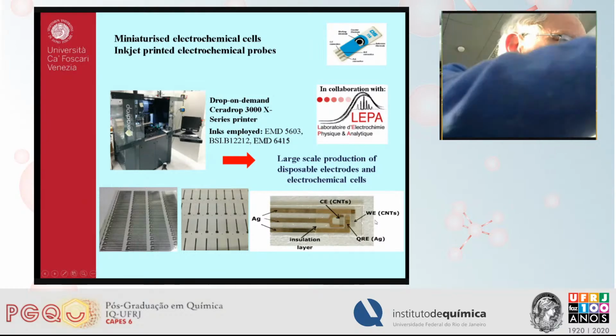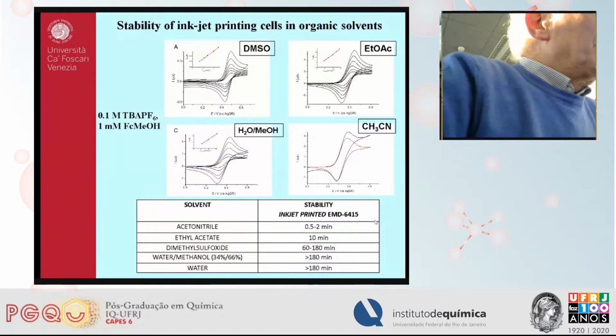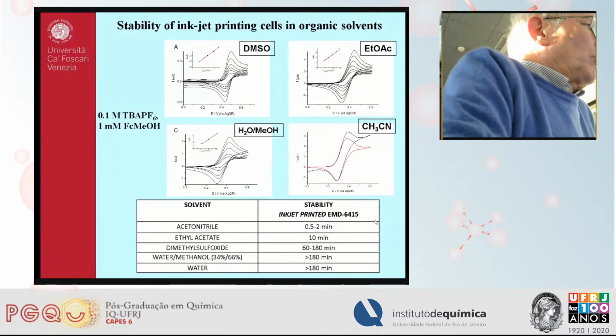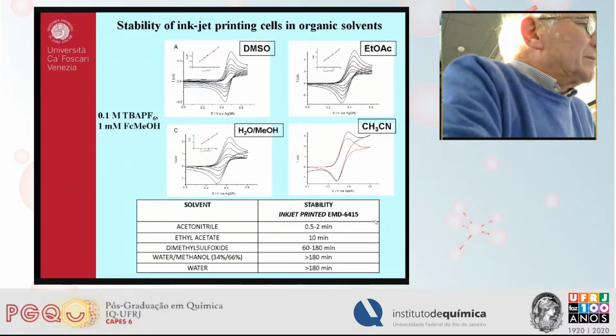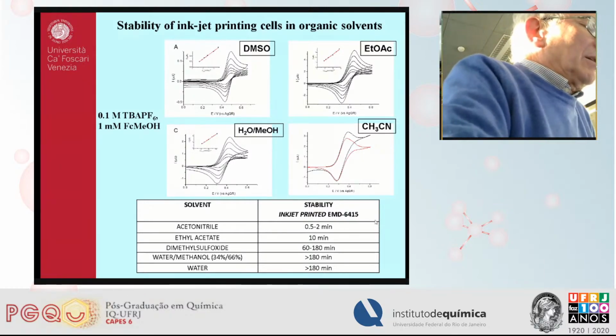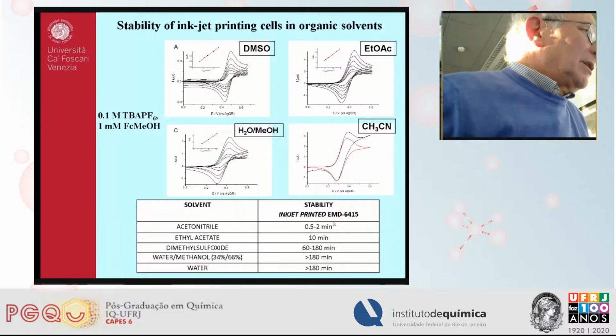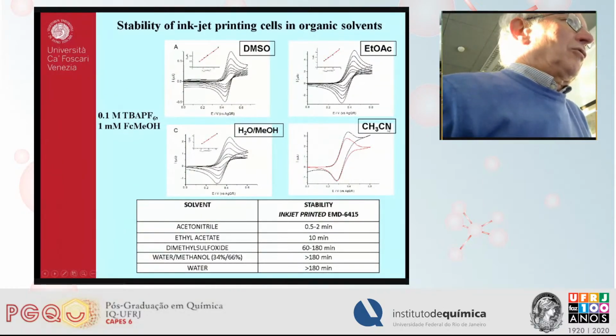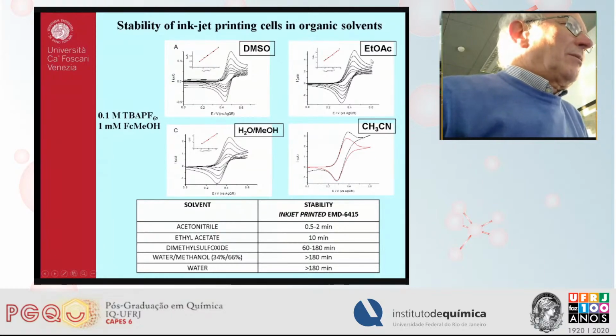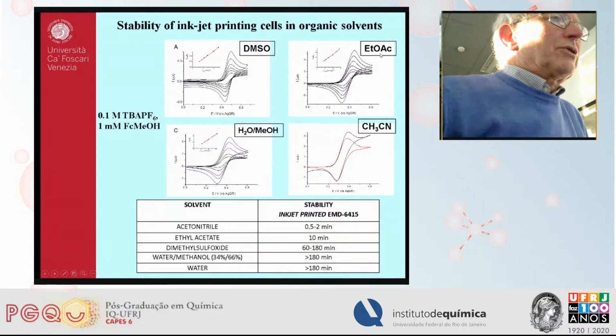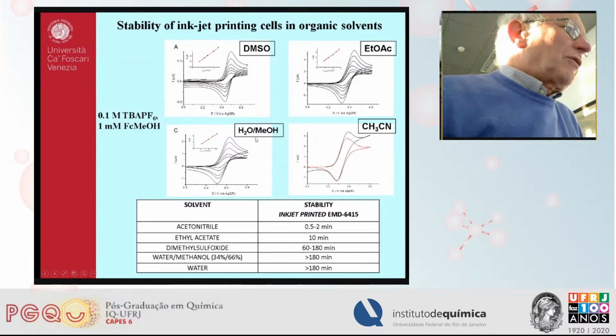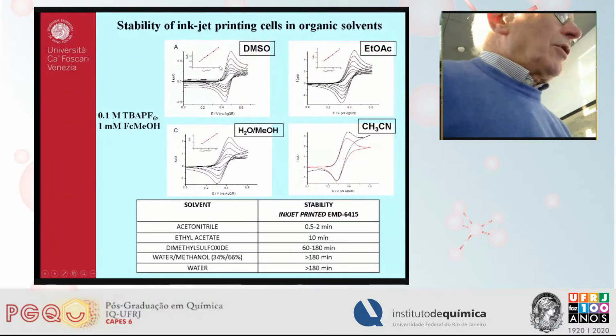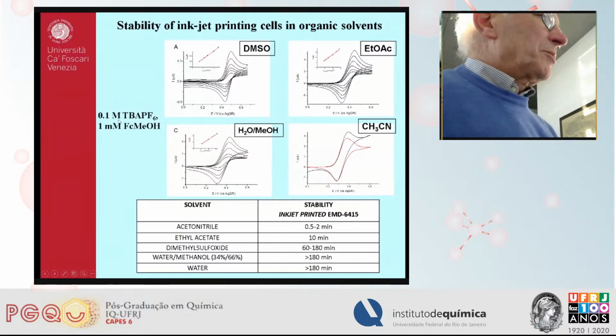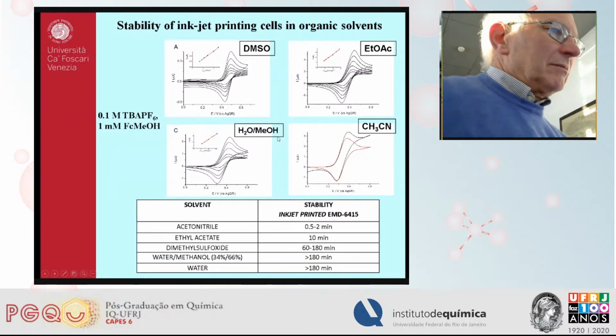So we tested this electrode prepared with these new inks using a normal probe, which electrochemists know, ferrocene methanol, in order to test the stability of this electrode in organic solvents. We used, apart from ethyl acetate and acetonitrile, which were those of interest for us, also dimethyl sulfoxide and mixtures of water and methanol. So here are typical cyclic voltammograms we obtained for this probe at different scan rates, okay? And we tested the stability with time.